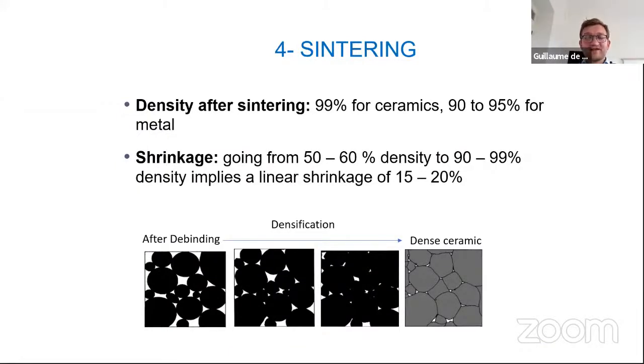What is sintering exactly? Sintering is the kind of densification which happens while the material stays solid. We're not melting the material, of course, or we would lose the shape. We're just densifying it at very high temperature. We go to densities up to 99% for ceramics, usually more than 90% for metal, which means a shrinkage. If you start with a part which has a density usually between 50 and 60% once you have removed the binder, and you want to go to 90 to 99%, there's no miracle.